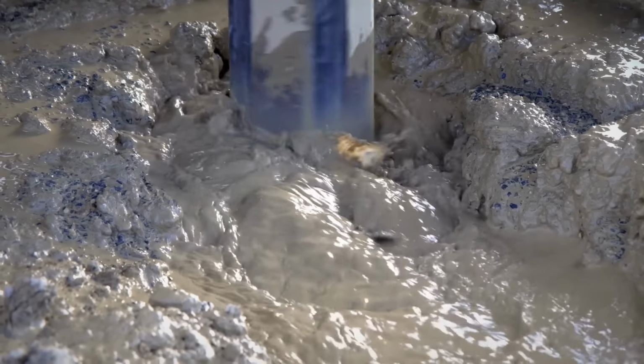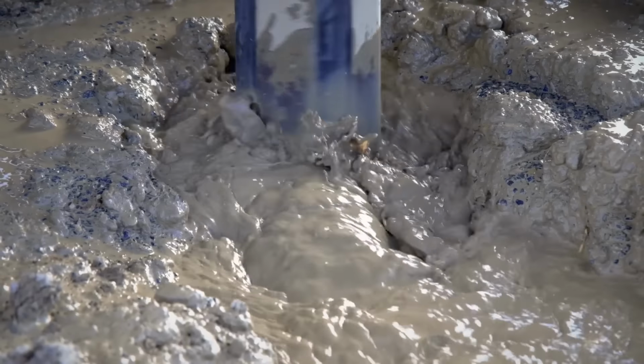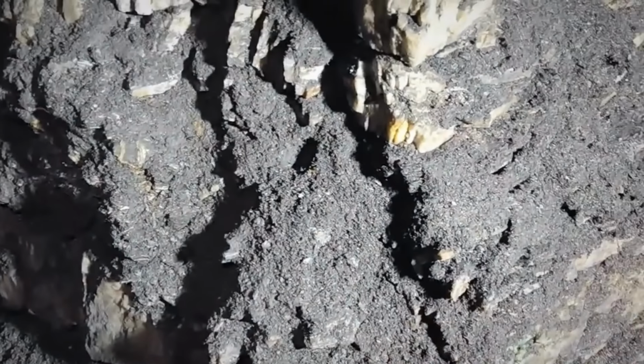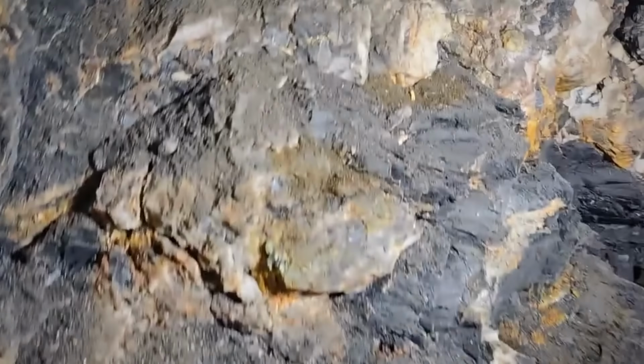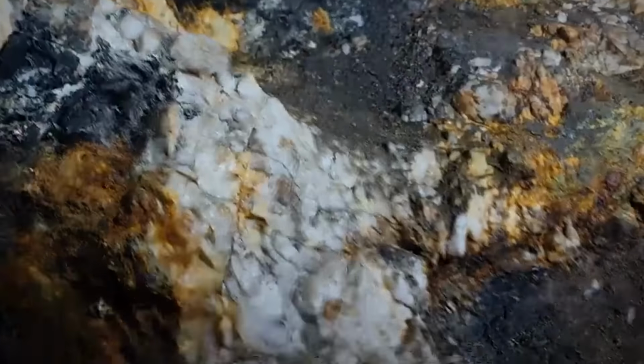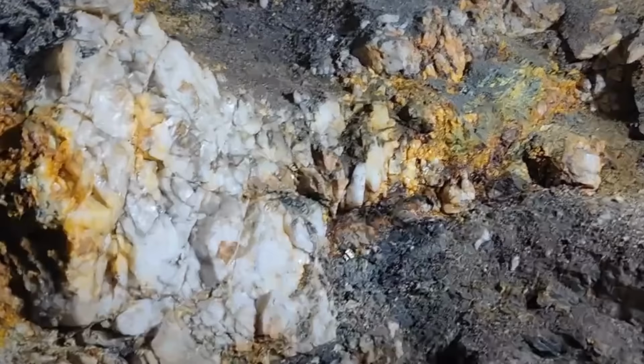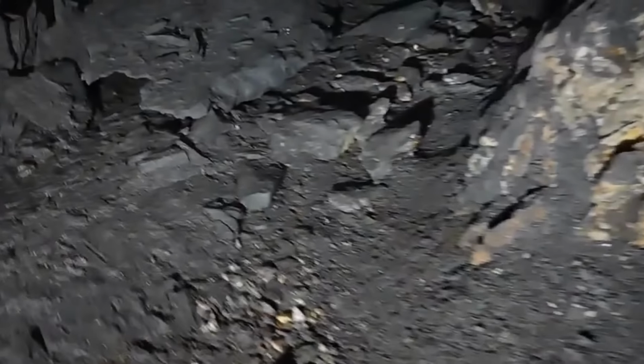Some kits use acid digestion followed by colorimetric strips or chemical precipitation to identify gold in crushed samples. Others involve cyanide or thiourea leach solutions that dissolve free gold over hours or days. These methods can confirm presence, but are sensitive to contamination, sample prep, and reagent accuracy. DIY fire assays, though theoretically possible, are dangerous and legally restricted in most jurisdictions due to the use of lead, high temperatures, and toxic byproducts. Unless performed in a lab setting with proper gear, they risk more than just bad data. However, simple bottle leach tests or gravity-based methods, such as sluice mats or shaking tables, can provide semi-quantitative reads if you're working with visible gold or rich concentrates.